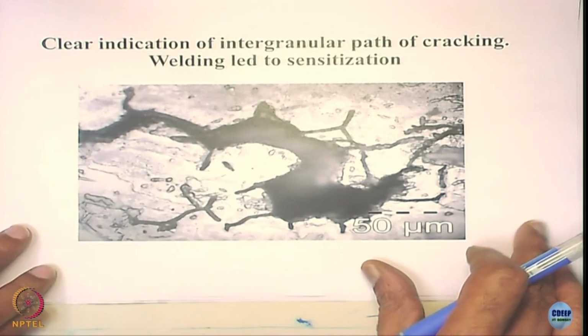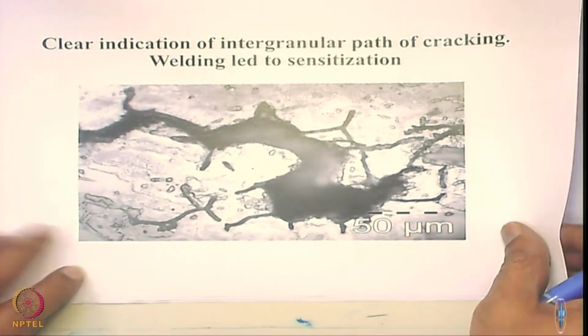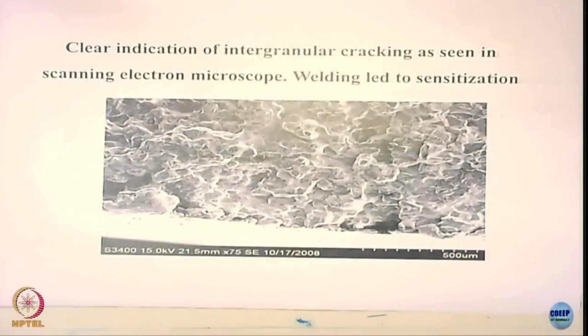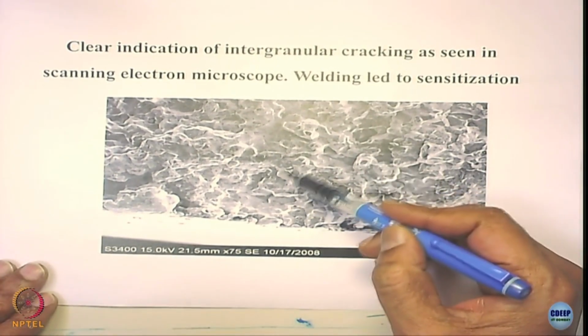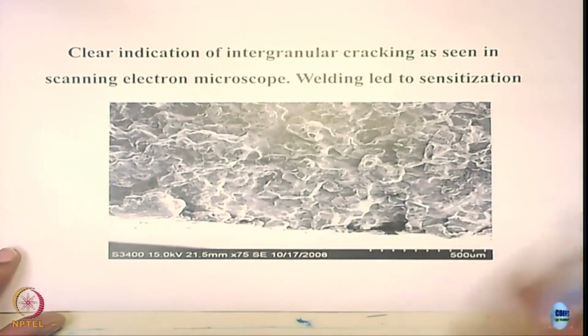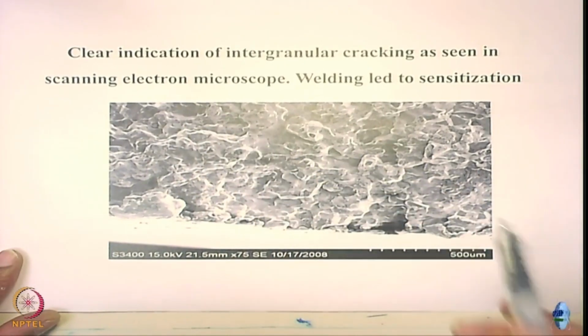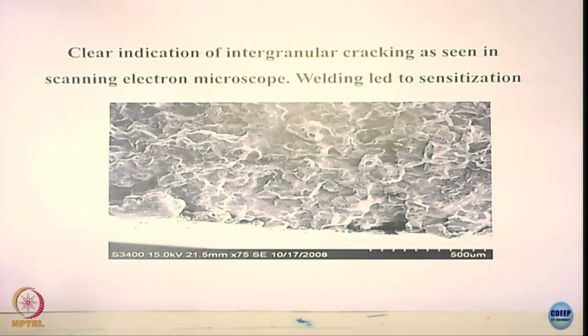You break open this, you look at the crack plane, you will be able to see nice grains which are not elongated, right? You can look, these are all grains. You see the grain facets, clear grain facets. The grain facets mean the grains are not deformed, like sugar grains, you see that, right. So they are not deformed.